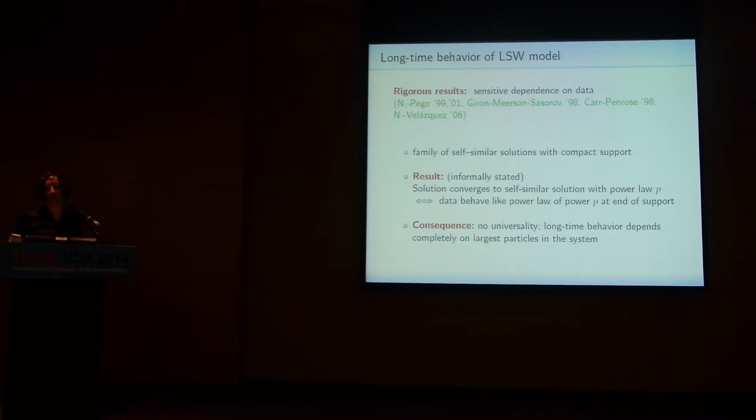And in some sense, for a PDE person, it's not so surprising, because the LSW mean field model is a pure transport equation, so it remembers somehow the details of the initial data forever. But so we can say, as a consequence, within the LSW mean field model, there's no universality. The long-time behavior depends extremely sensitively on the initial data, and more precisely, it depends on the largest particles in the system. Okay, so this is one disadvantage. In some sense, the mean field model is too degenerate. But then there's another problem,